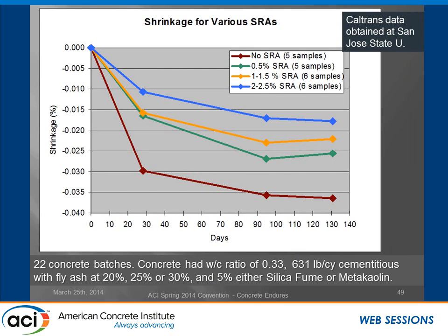These kinds of graphs are produced all over the place. This particular one was done at San Jose State on a Caltrans project here. It was done when we were in the design stages of the skyway that you heard about earlier, and wanted to control, not for shrinkage, but for geometry control in this case. Nonetheless, we got the data here, and you can see that these SRAs were readily available on the marketplace, cut into the shrinkage by quite a bit.